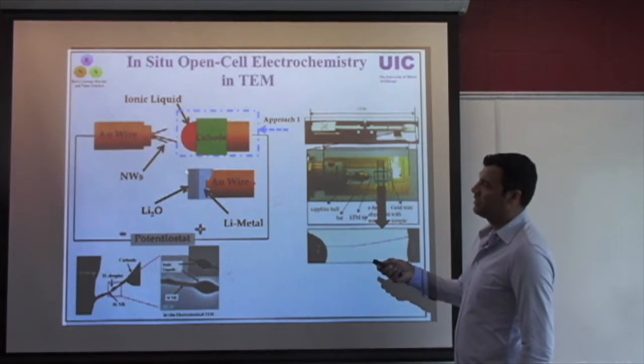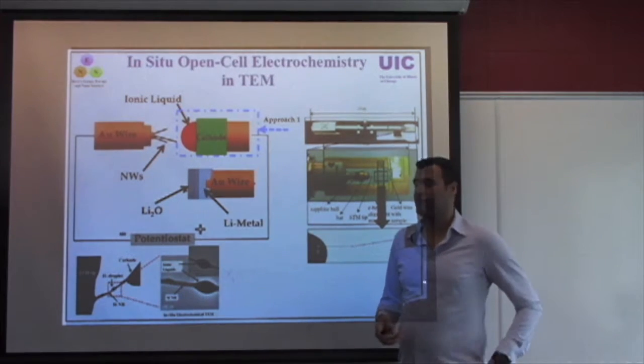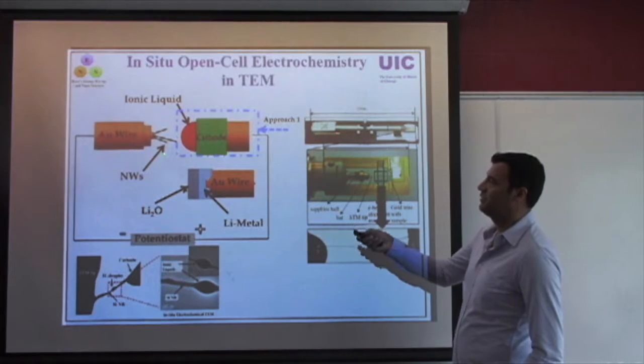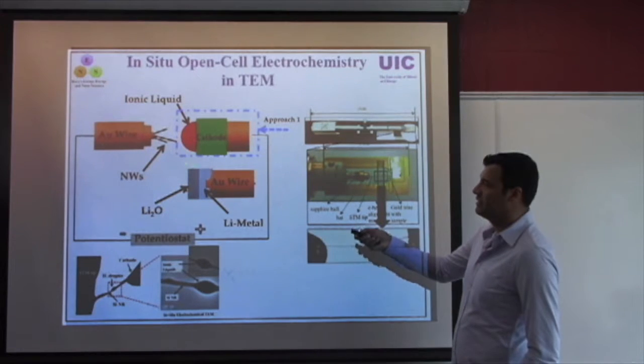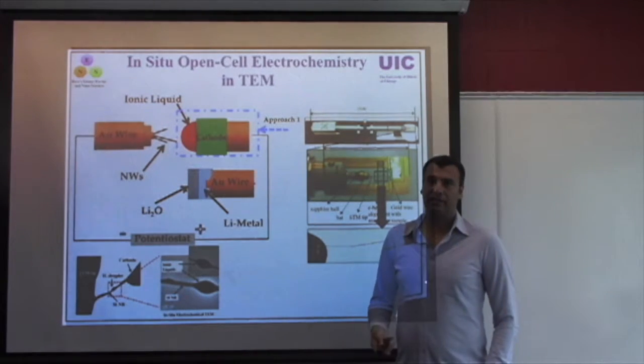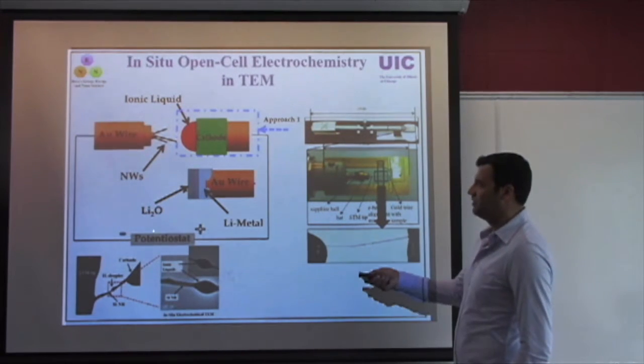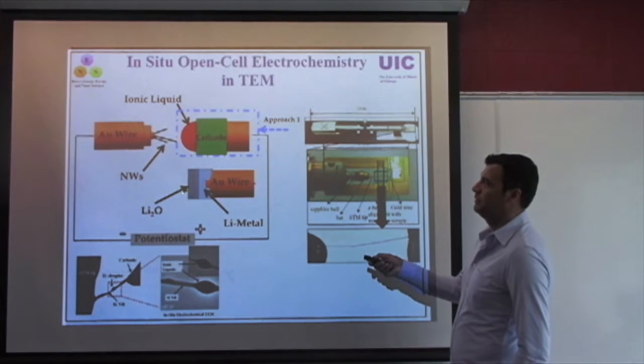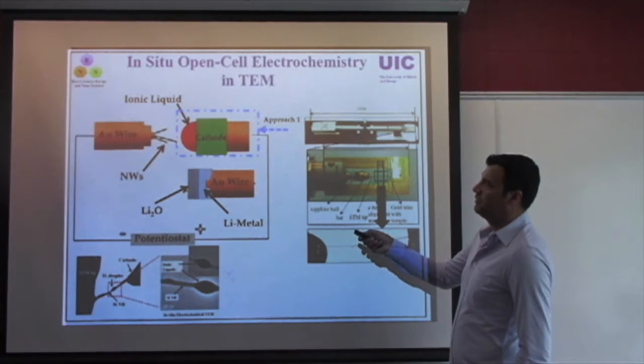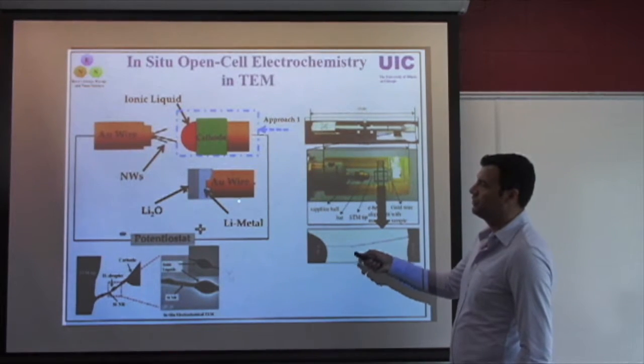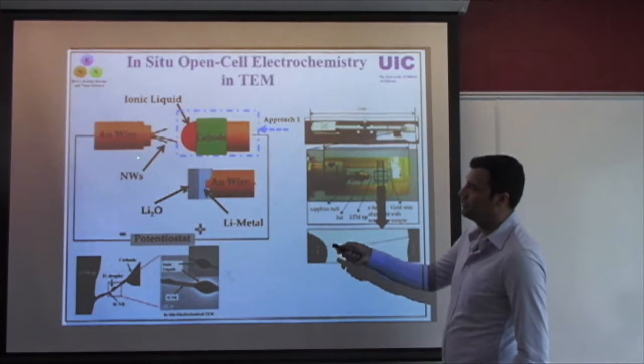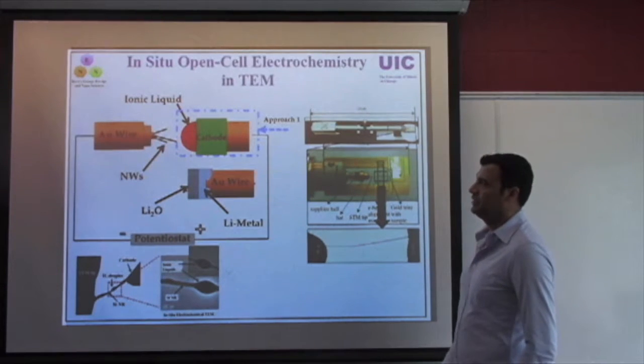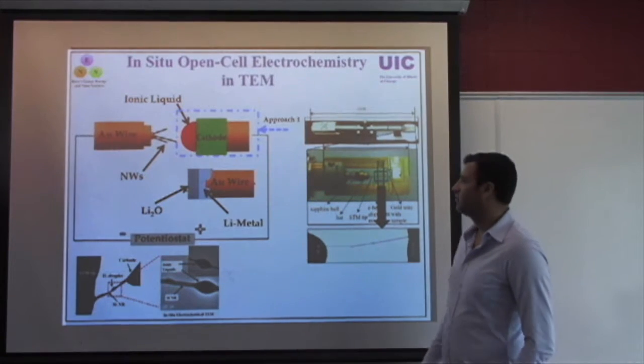Another nice system which allows you to do the point contact sort of electrochemistry research is based on using lithium metal, which has a lithium oxide at the surface in the form of Li2O. And when you make a contact between your electrode and this interface, then you can apply a potential and then drive the lithium to go from this side to the other side, and then keep track of the behavior again.